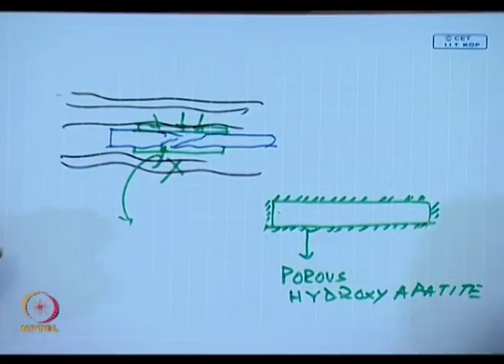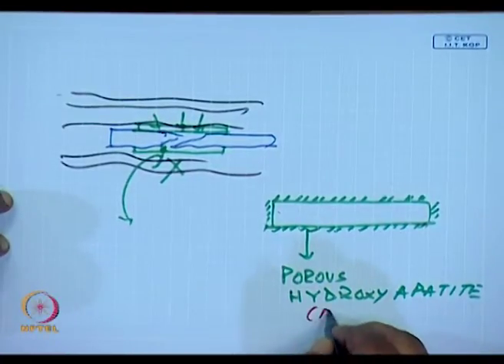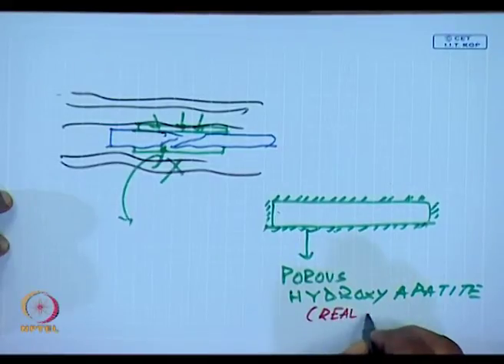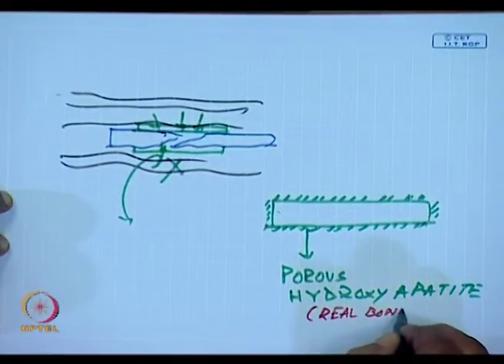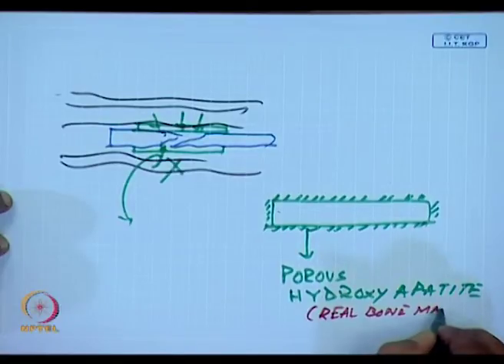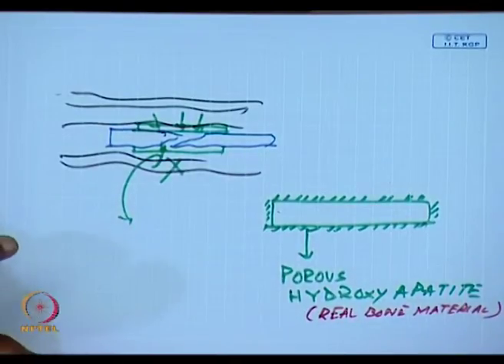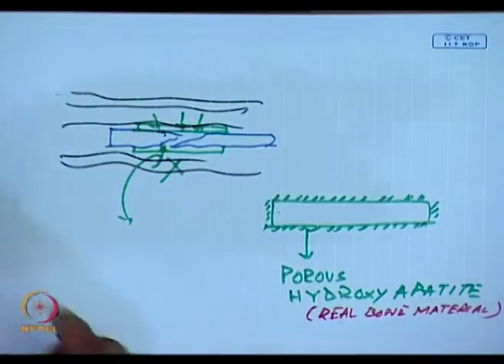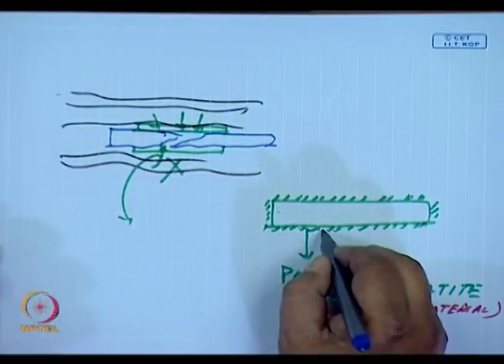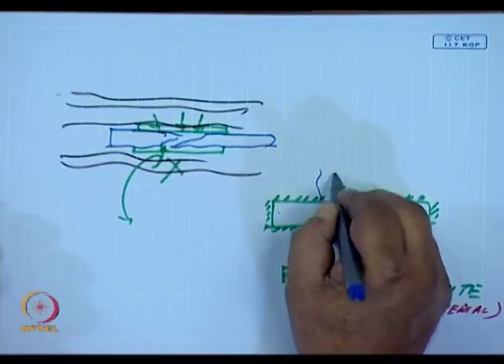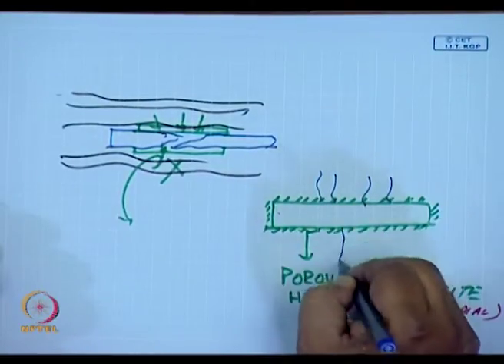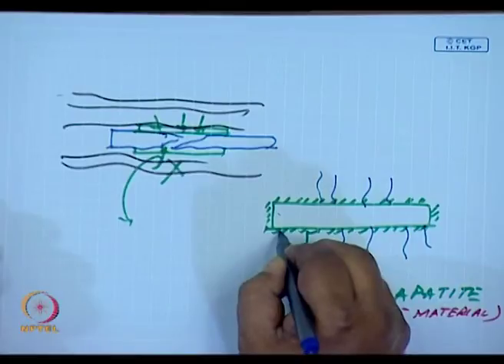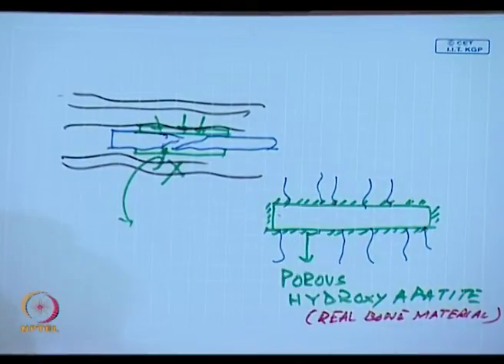This hydroxyapatite is a real bone material. True, we make it, we synthesize it, but this is porous. And because it is porous and it is very well adherent to the titanium plate, muscles can grow in. And the titanium plate does not come loose from the muscles.